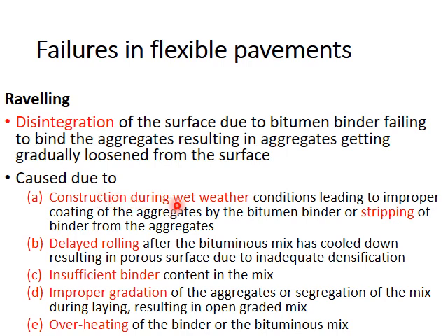construction during wet weather conditions, that is presence of moisture attacking the bitumen binder and causing the aggregates to detach from the pavement surface. Also delayed rolling, that is the mix is not hot when it is compacted, it has cooled down, which we talked about in the construction process. That is, once the hot mix is brought to the site, it must be spread, rolled and compacted as soon as possible without allowing it to cool down.